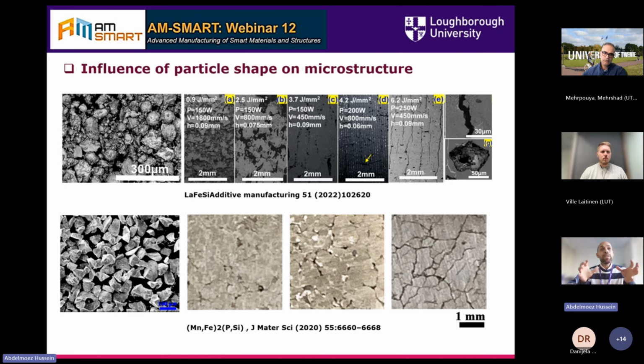This is, of course, related to the processing parameters, but it's more likely related to the flowability of the powder. They do not flow nicely due to the rocky shape, or the more satellites they have. So they have another defect added to the process, and you can't get rid of it, even by changing processing parameters.